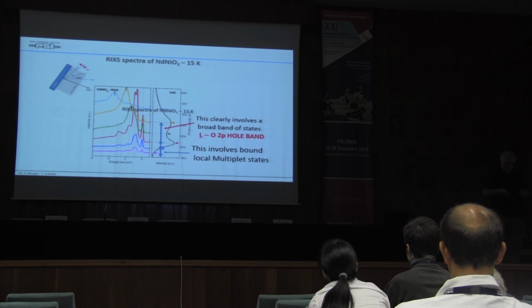Now, their data showed the following. We saw the X-ray absorption spectrum on the nickel edge now, the nickel 2p to 3d transition, looks like this. Okay? And this is 850 electron volts here in this ring. So, and we always thought that this two-peak structure and stuff like that was because of the multiplet structure that you have with one hole in a 2p and a 3d8-like final state, because you've moved that electron up to the d shell. Well, and many people tried.